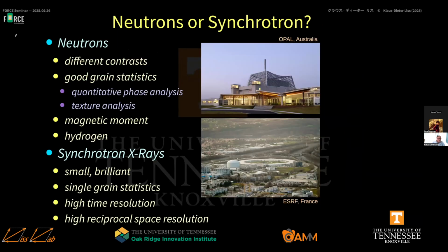And the question now is, do we want to use neutrons or synchrotron X-rays? They all have their advantages and disadvantages. So neutrons have a very different contrast and large penetration into the material. That's why we get a good grain statistic for quantitative phase analysis or for texture analysis, where you have to average over many grains. Neutrons also have a magnetic moment, and see hydrogen very well.